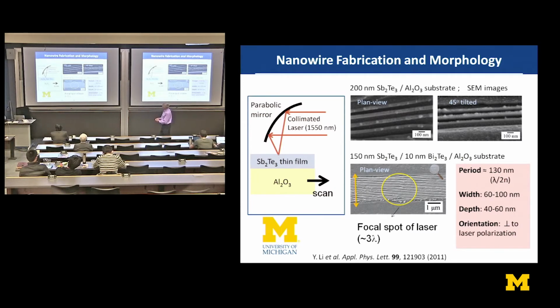Why were we so surprised? Because the size of our laser spot, diffraction limited to about three times the wavelength, which is about 3 times 1.5 microns, 4.5 microns in diameter, was much bigger than the features we were seeing produced on the surface when we scanned this surface underneath the laser beam with the polarization of the laser oriented perpendicular like this, in other words, perpendicular to the scan direction.